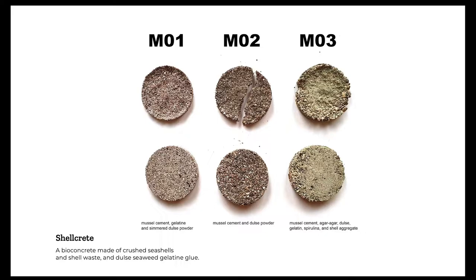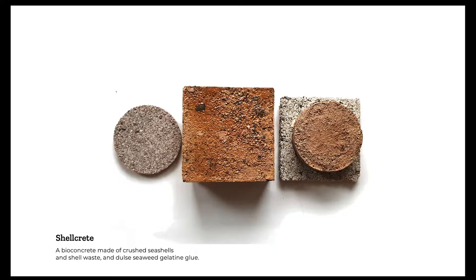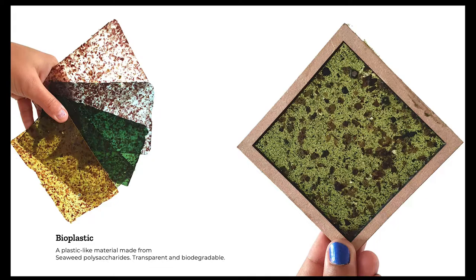I was able to come up with different mixes of algae glues and also animal-based glues to come up with a working ratio. Not all my ratios worked — some were quite fragile — but adding gelatin and animal glues in particular really increased the strength of the material. An initial compression test showed the material is very similar to concrete. The beautiful thing about this material is that depending on the shell species you use, you end up with a completely different color — mussel shells create a beautiful white shellcrete, while cockle shells produce a reddish-brown, almost brick-like color.